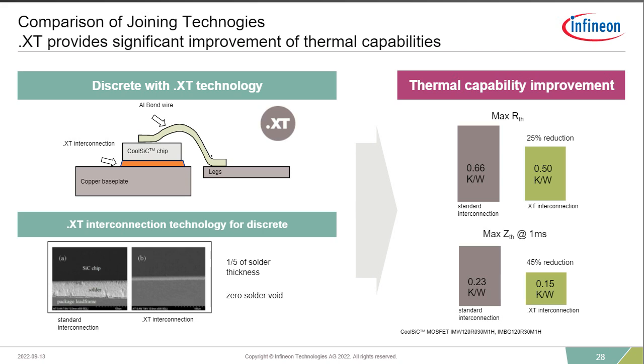So what you get is about a 25% reduction in the R theta of the device, as well as a 45% reduction in Z theta in the application. So really providing a device that provides you the best performance and the best thermal cycling capability. And particularly exciting too when you talk about how much smaller the die sizes of silicon carbide are versus that of IGBTs or silicon MOSFETs. This provides a big advantage for the customer in terms of performance in the application and keeping the junction temperatures lower so that you can drive more power density in your application.